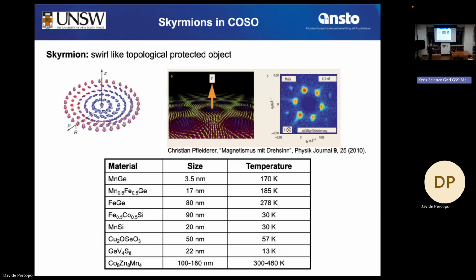What do you look for when you're looking for a new material? Like when you jump to the next material, say if you want to achieve a higher temperature, are you just experimenting to see what works? Are you looking for a particular structure? Yes, exactly. Structure, that's the key word. We need a so-called non-centrosymmetric crystal to get a spin spiral. Centrosymmetric means if you have a cube and an atom in the center, that's perfectly symmetric, but that atom needs to be slightly displaced, non-centrosymmetric, and that's one of the crystallographic reasons why we get skyrmion structures. So that's the first starting point.